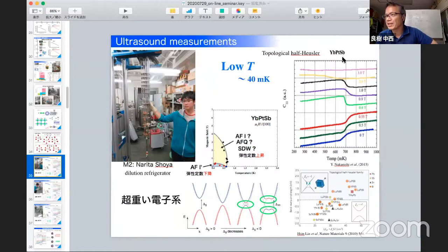Ytterbium platinum antimony. It's one of the highly correlated electron systems, containing one of the rare earths, ytterbium. This one shows the temperature dependence of elastic constants. One mode, C11. As you can see, the elastic constant decreases on lowering temperature like this. And since this system exhibits a magnetic transition, we can observe a clear step-like behavior at around 700 millikelvin.